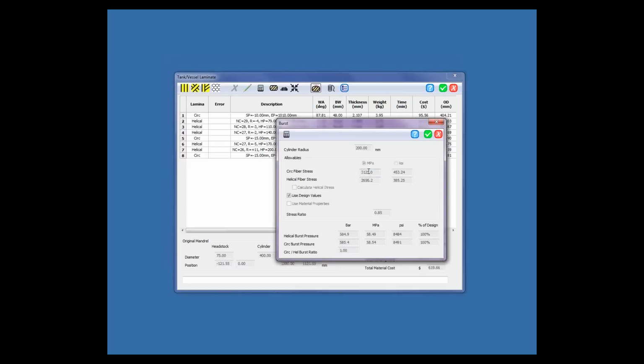we have a circ fiber stress of 3125 megapascal, and helical fiber stress of 2656 megapascal for a stress ratio of 0.85 between those. That's a typical value for these types of tanks. Some people might go a little higher. But like I say, we want the stress to be primarily in the circumferential direction so that the failure mode is in a certain direction. Now we come down, we look at our design pressures, and we say, oh, over 100% of our design pressures. It took me about 2 hours to actually do that, so it came out exactly 100%.